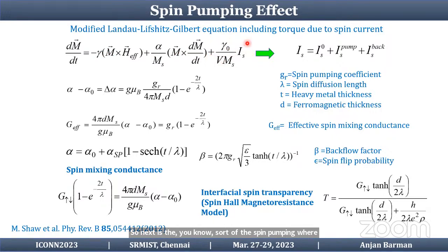Next is spin pumping, where we can write down the Landau-Lifshitz-Gilbert equation like that, and here the extra spin current term has both the spin pumping term and the backflow term. Using this ballistic model we can write down the modulation of damping as a function of both the ferromagnetic layer thickness and the non-magnetic layer thickness, where lambda is the spin diffusion length. And we can find the effective spin mixing conductance, the intrinsic spin mixing conductance, as well as the spin transparency.